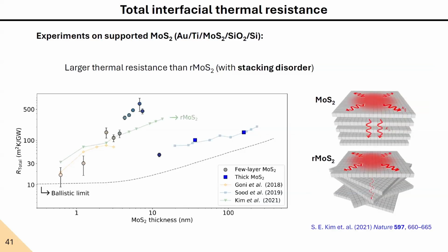Well, here it is only covered by these results by Sood et al., where they study randomly oriented molybdenum disulfide. This means their materials are polycrystalline, and therefore the stacking between the different layers is random. So they should be more resistive than expected. However, our flakes show an even higher thermal resistance. So could it be that coherent phonon effects are present in our experiment?